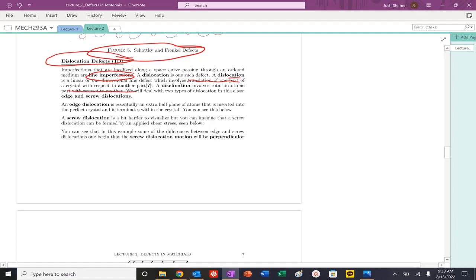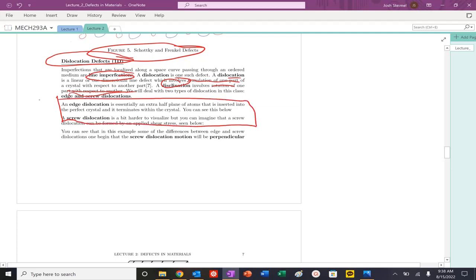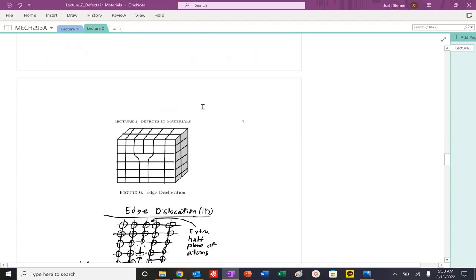A disclination is basically a rotation, a twist of one crystal structure. But we're going to be focused on edge dislocations and screw dislocations. Screws can be right-handed or left-handed. Edge dislocation is this extra half plane of atoms that's inserted. You can see here, I've got a perfect row of atoms, perfect row of atoms here, and then now this half plane of atoms doesn't continue. I'm putting this unfinished plane of atoms here instead of these perfect structures.